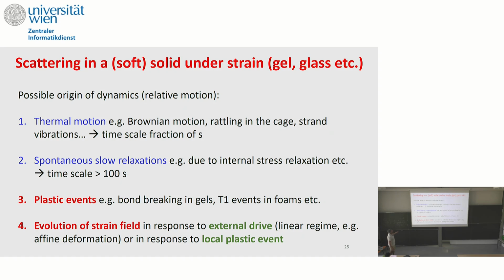There may be slow relaxation. This is typical of samples like gels and glasses. In principle, you would think that everything is frozen, with no possibility of really changing the particle positions a lot, but experimentally, people have found out that that's not the case. There are very slow relaxations. They might be related to thermal motion on very long time scales. They might be related to internal stresses that are frozen in when you prepare your sample, and Mehdi has mentioned that. The time scale here is typically hundreds or thousands of seconds, okay?